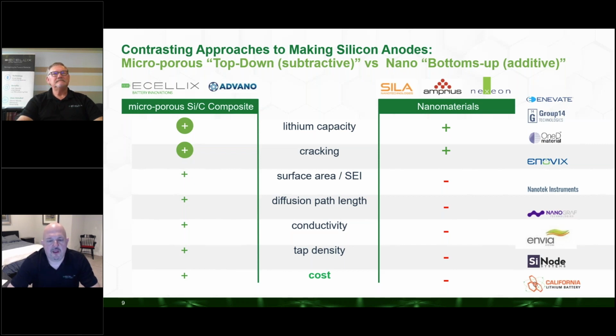Most of them are predicated on the idea of nanotechnology, using small nanomaterials that solved the problem of this cracking. When the particles got small enough, when they expanded and contracted, they didn't break. So silicon was able to hold more lithium, and they were able to make it so that the silicon was not cracking and breaking apart. But as they built it, they had a huge problem with creating surface area. They had a problem with all the other dynamics happening inside of the battery. And in the end, what it leads up to is a material that is very expensive.